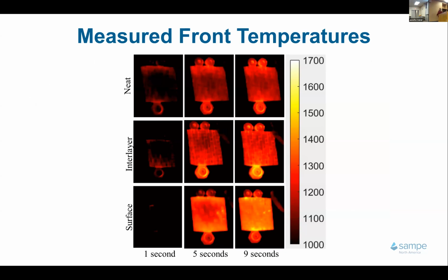So here's a summary of measured front side temperatures. We have the neat, we have the inner layer, we have the surface layer, at 1 second, 5 seconds, 9 seconds. You can see the surface layer being achieved, this interlayer, and these are the ones without it at all. You can see there's some increase in heat signature on the surface of the surface layer. We don't at this point know if that's a good thing or a bad thing yet. It could be that it's isolated there and not transferred to the back. At this point, we don't know.